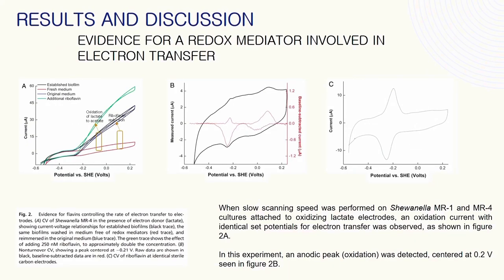Results and discussion: evidence for a redox mediator involved in electron transfer. When riboflavin was added to sterile electrodes and growth medium, peak height and potential were identical to those observed with the culture supernatant. Riboflavin 5-phosphate produced a peak centered 3 millivolts more negative than riboflavin, indicating that these flavins are indistinguishable, especially where small pH changes can lead to potential changes.